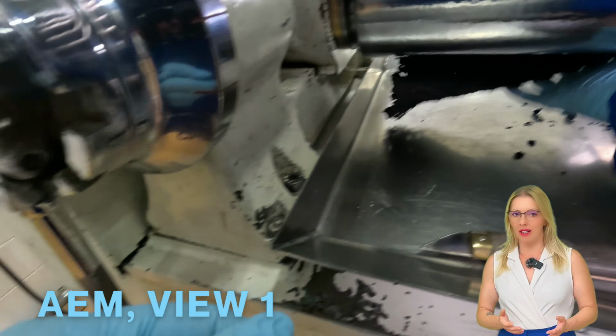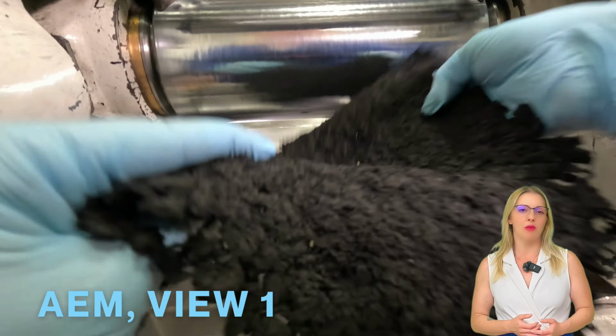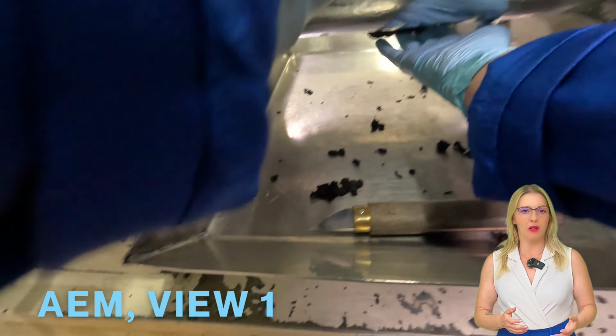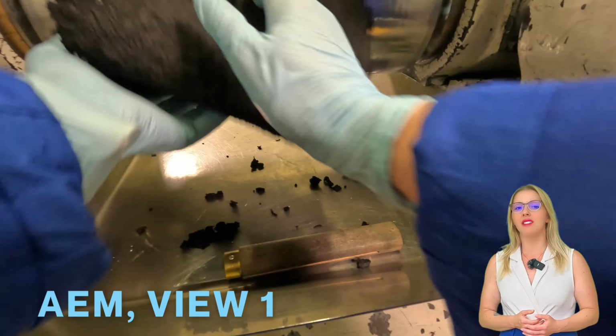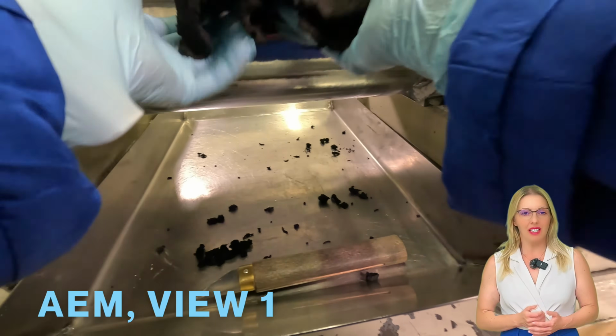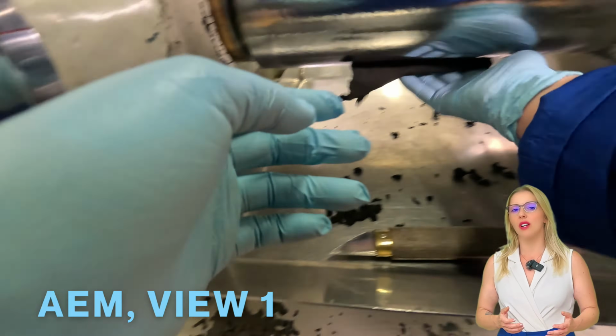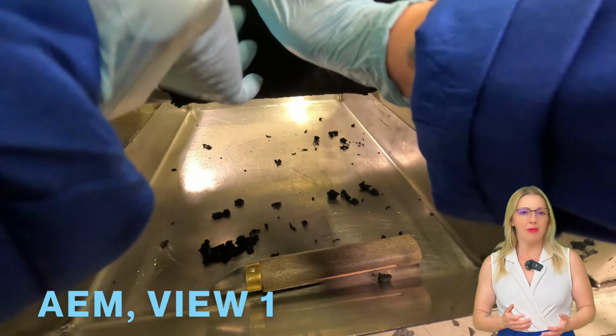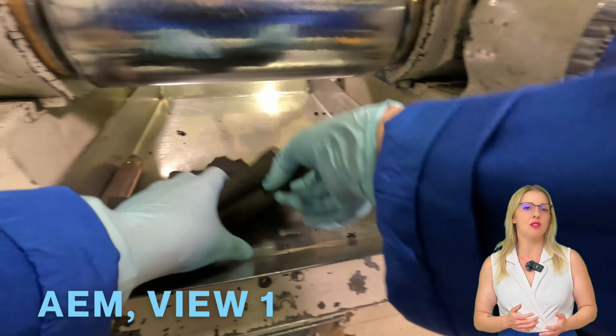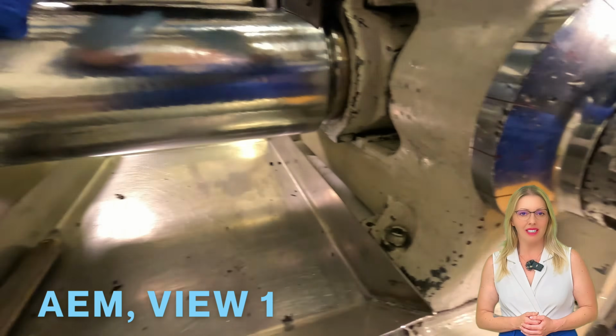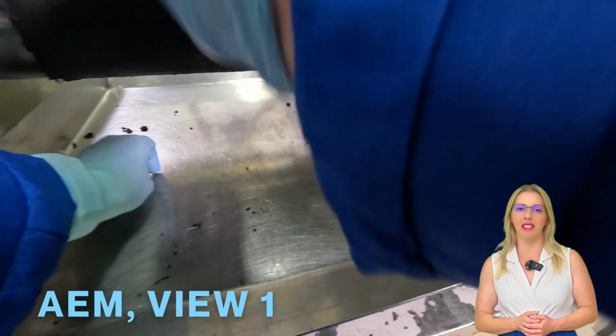The AEM compound, on the other hand, looked unpromising at first. It was powdery, crumbly, and hard to gather into a sheet. But after working it on the mill, the structure improved visibly. It began to form a consistent sheet with a smooth surface, and by the end, it showed excellent processability.